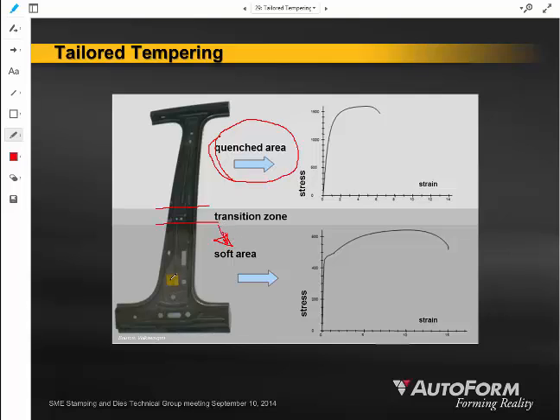or quench slowly. So the die at the bottom portion of this B-pillar is being maintained at around 400 degrees Celsius. And by holding that die warmer during the forming operation, we ensure that its microstructure is different than the top half, which is being cooled to 80 degrees Celsius. And that means that we're going to have a much higher strength material at the end of the forming operation for this top part of the B-pillar, and then a much lower overall yield strength and tensile strength of the lower portion of the B-pillar.